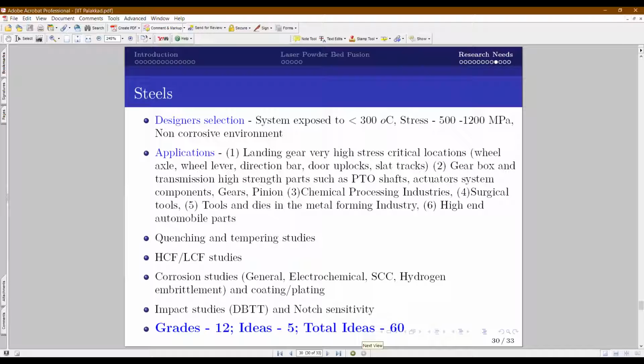Steels, although not so popular in aerospace, but still we use the high-end steels in aerospace applications. When the system is not exposed to more than 300, and stress levels are in the order of 500 to 1200 MPa, and if the environment is not so aggressive, like a corrosive environment, then steels are generally chosen. So most of the components you find in landing gear, high stress critical regions like slat tracks, door uplocks, wheel axles, and so on. All the gearbox, transmission, high strength parts like PTO shafts, power take-off shafts, actuator systems, gear pinions.